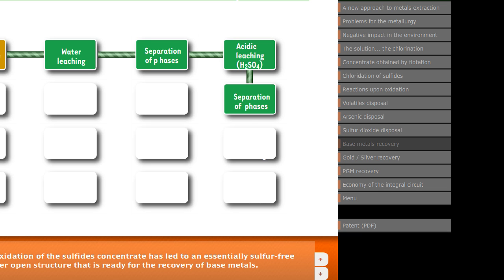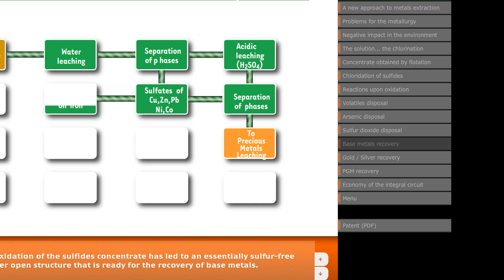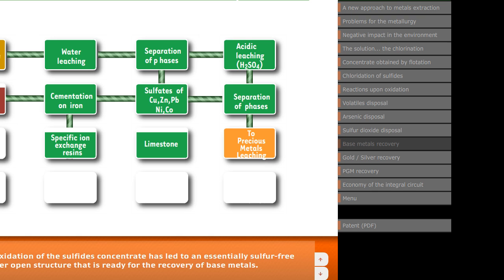The separation of metals calls upon collection of copper by cementation, followed by nickel, zinc, and cobalt recovery by specific ion exchange resins, and completed by lead precipitation as chloride. The pH of the resulting solution is then raised above 6 by limestone addition, and with aeration, the sulfates and iron are precipitated. The water can be recycled after sedimentation in a settling pond.